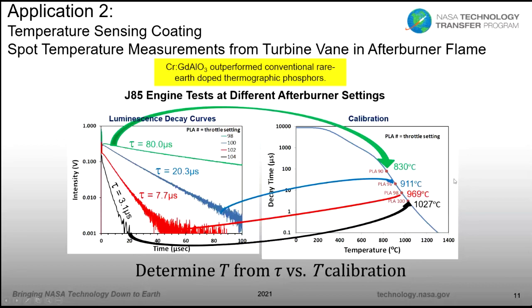I should say that when we went out to AEDC, we also did this with some other vane doublets with different thermographic phosphors, with more conventional rare earth doped ones. And our chrome gadolinium aluminate substantially outperformed those in terms of having a much higher intensity emission and therefore better signal to noise, better temperature precision for these measurements.